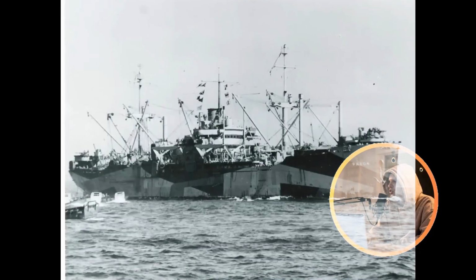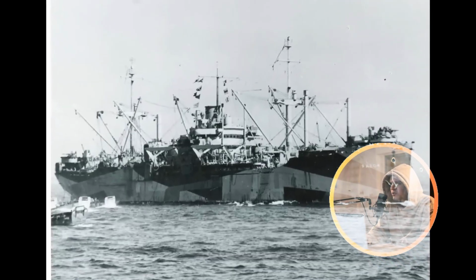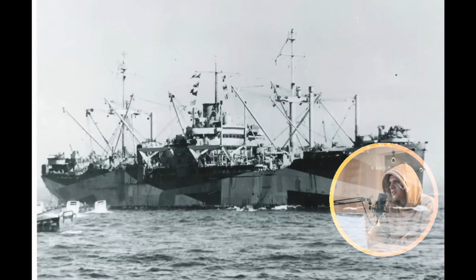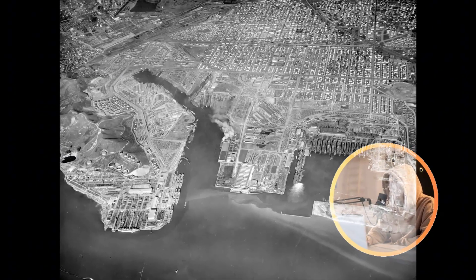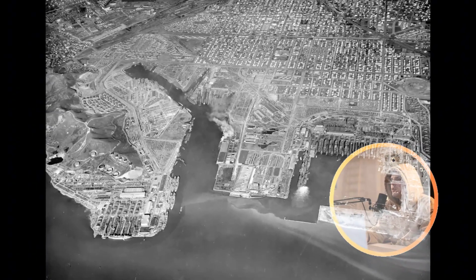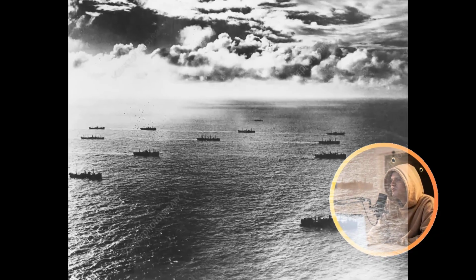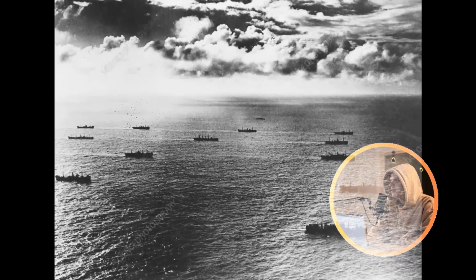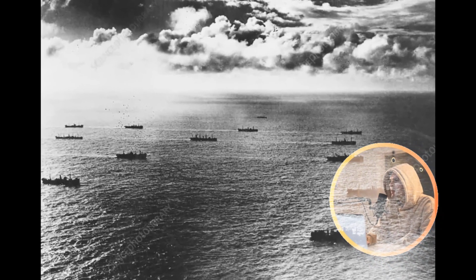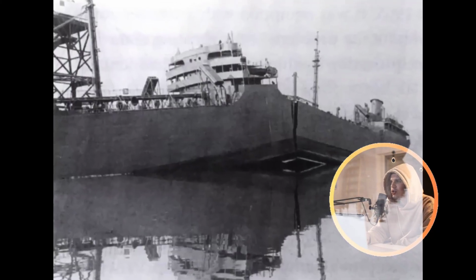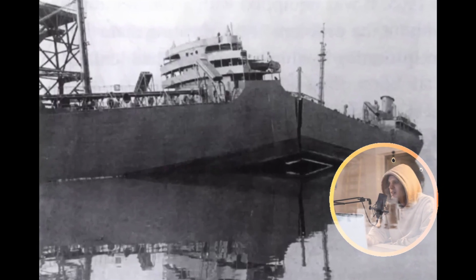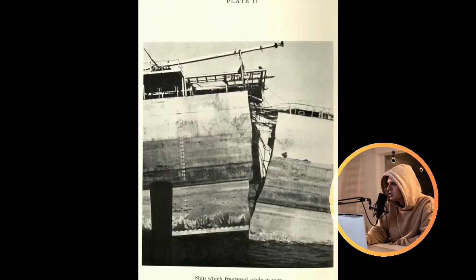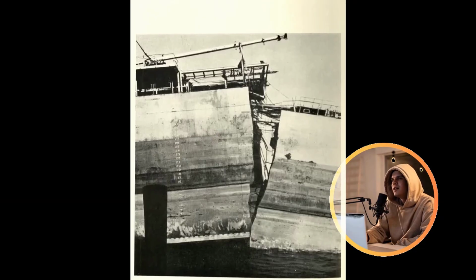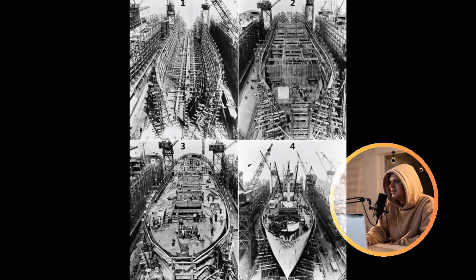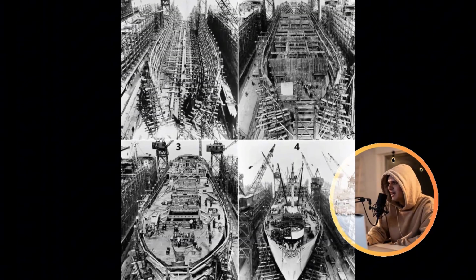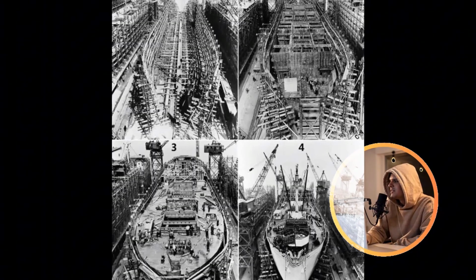The ramifications of unchecked failure propagation quickly extended beyond mere structural integrity. A stark and undeniable economic assessment underscored the rationale for change. Each Liberty vessel, for instance, commanded a construction expenditure of approximately $2 million. In contrast, its successor, the Victory ship, incurred a cost of $2.6 million, representing a 30% increase in initial outlay. However, historical data up to 1944 revealed a troubling reality. A Liberty ship faced a 4.6% probability of experiencing a catastrophic structural collapse during its operational lifespan.